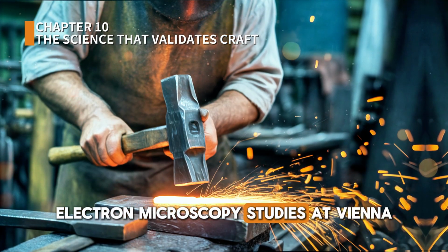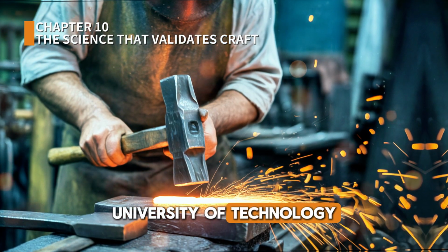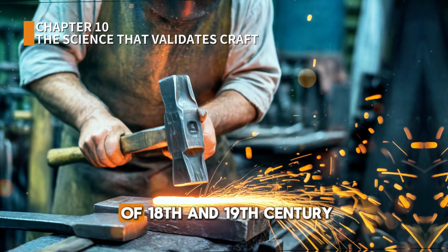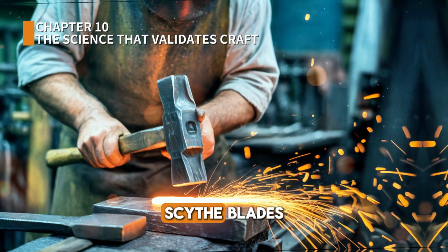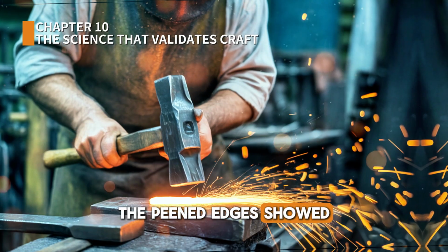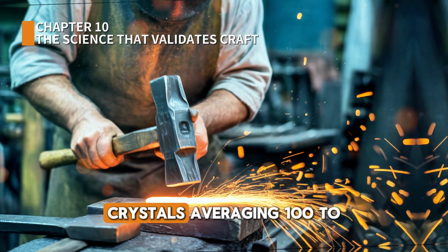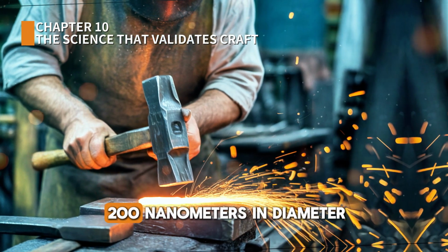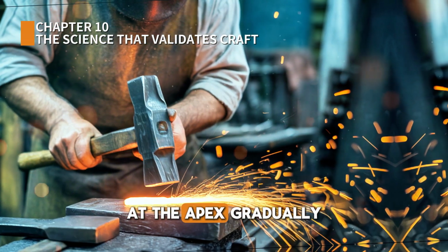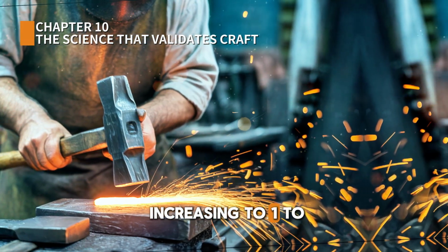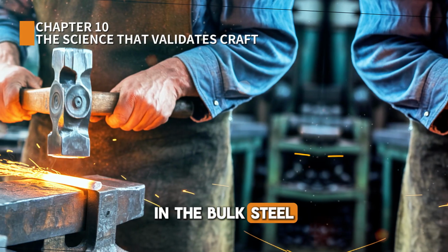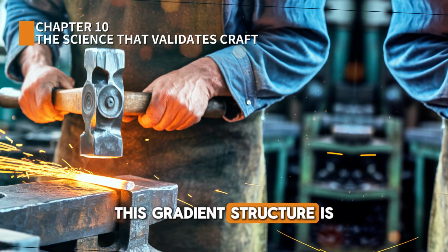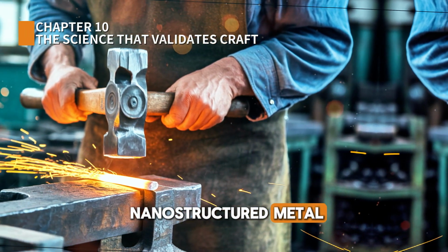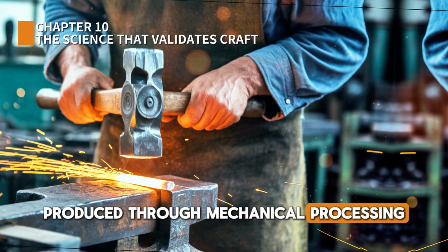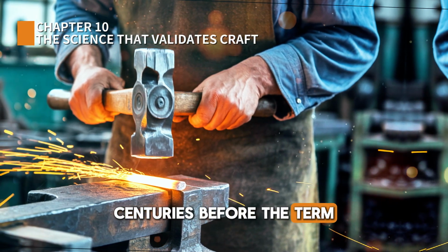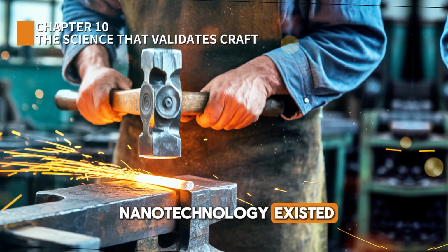Electron microscopy studies at Vienna University of Technology examined the edge structure of 18th and 19th century scythe blades. The peened edges showed extraordinary grain refinement, crystals averaging 100 to 200 nanometers in diameter at the apex, gradually increasing to 1 to 2 micrometers in the bulk steel. This gradient structure is nanostructured metal, produced through mechanical processing centuries before the term nanotechnology existed.